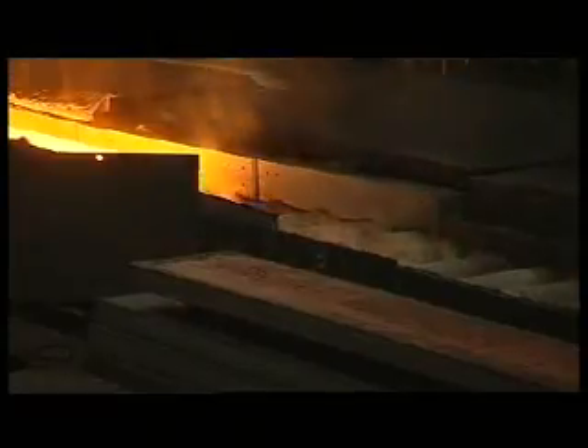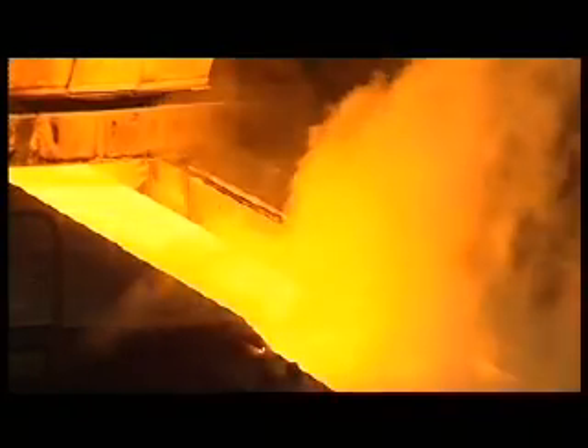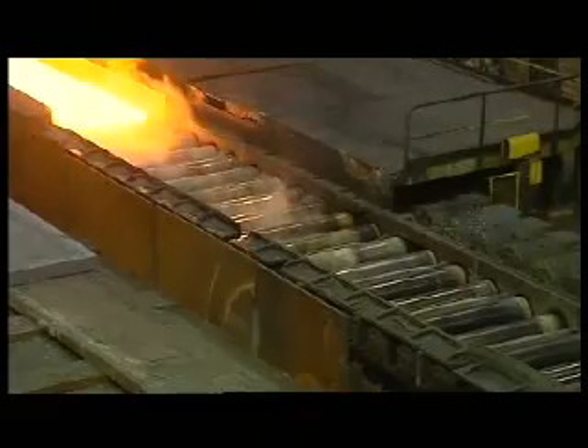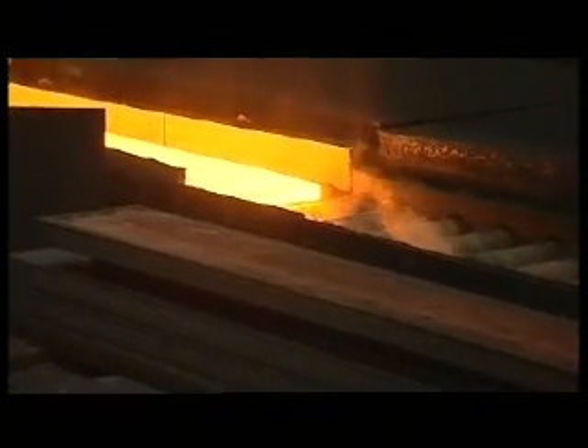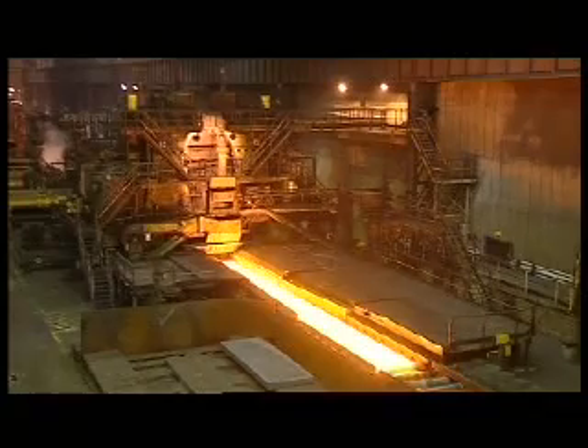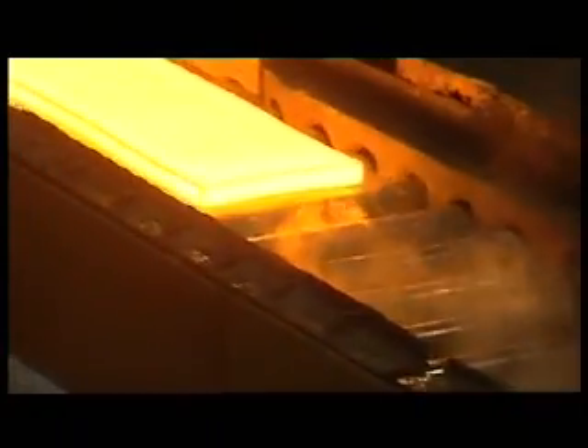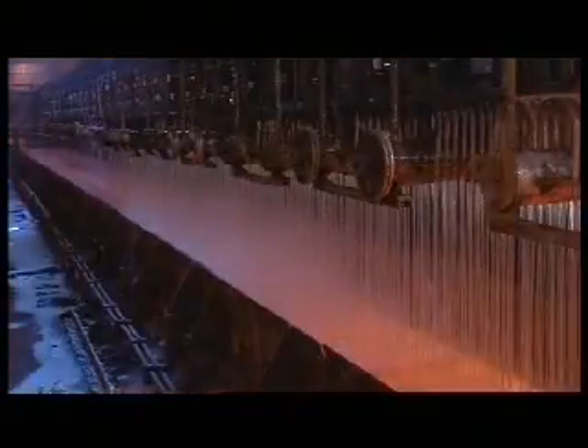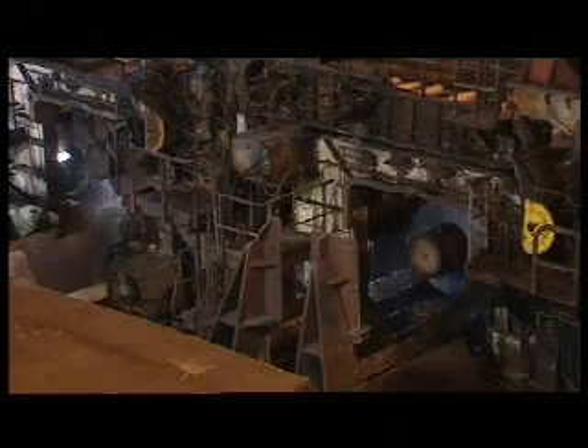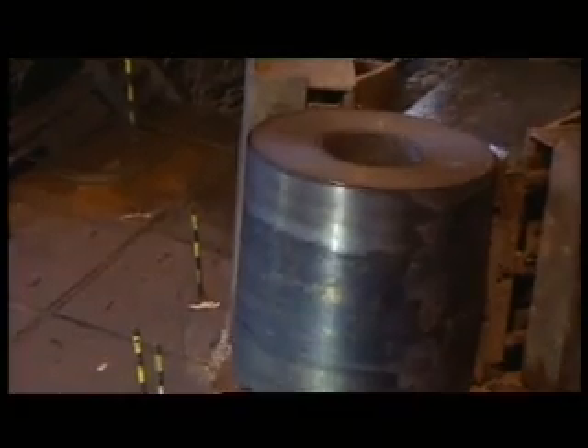In different movements, that is 2 roughing mills and 1 finishing mill, the 10-metre long and 22 centimetre thick steel slab is then reduced to a steel sheet several hundreds of meters in length with a thickness of between 13 and 1.25 millimeters. The finished strip is cooled by a series of powerful water jets in such a way that the strip reaches the coilers at the scheduled temperature range. Each coil is weighed and automatically given an identification number.